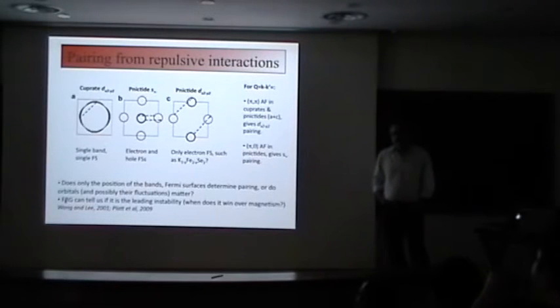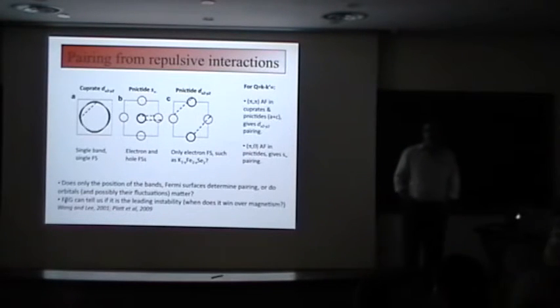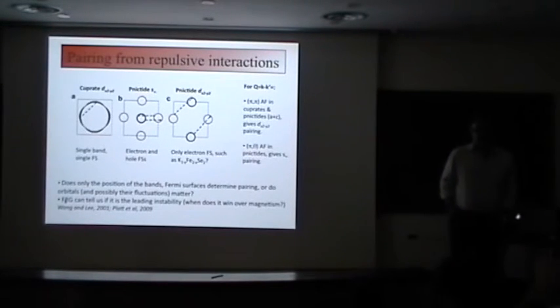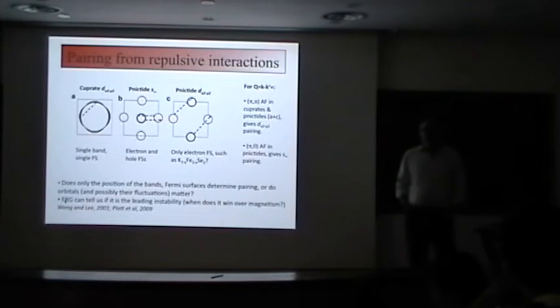So people tend to invoke this model of Fernandes and Chandra for the explanation, but what worries me there is that the relevant parameter for having two transitions or one is the dimensionality, the coupling in the third dimension. And what you have is either two second order phase transitions or a single first order phase transition on a line. So it would take a tremendous coincidence to be right at the critical endpoint of this single first order phase transition, and then with doping you split the transition.